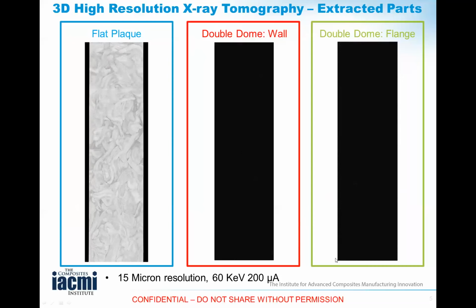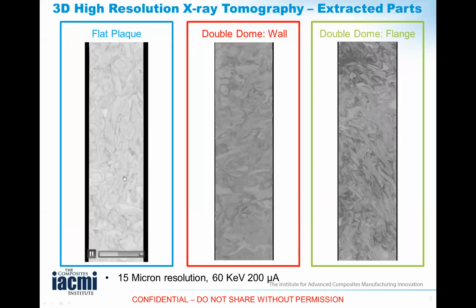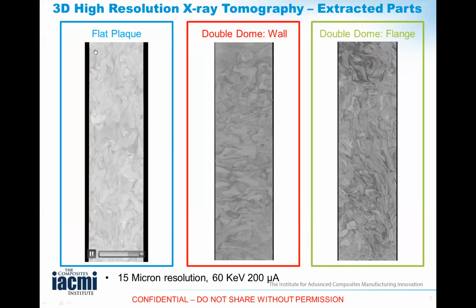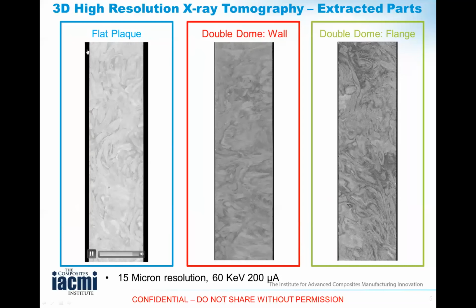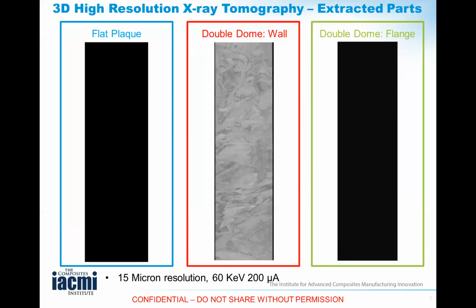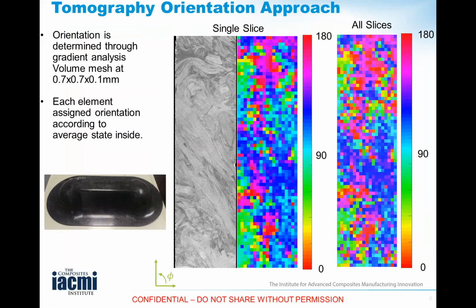So clearly we can see that there are fundamental differences in microstructure of these materials depending on where you extract them from, a molded component versus a flat plaque. And just to give you a sense of the size here, this is a coupon sample tested in tensile testing. So you're looking at a width of roughly 1 inch and a gauge section here of about 4 inches. It's a lot of work to generate this data on X-ray computed tomography, but what we get out of it is a very detailed view of fiber orientation.